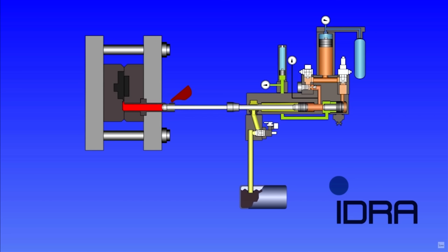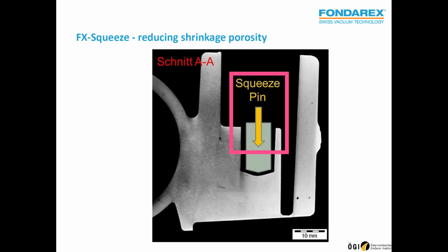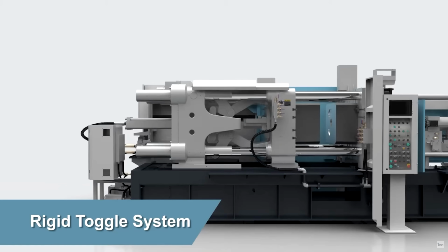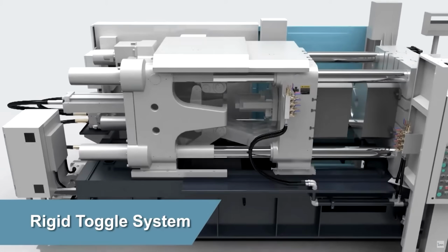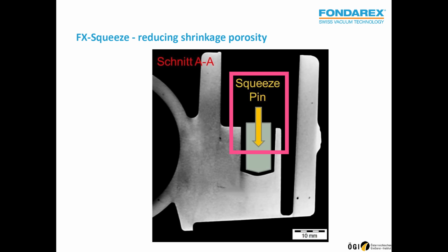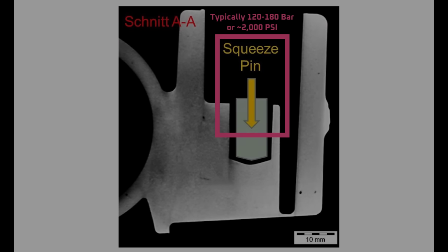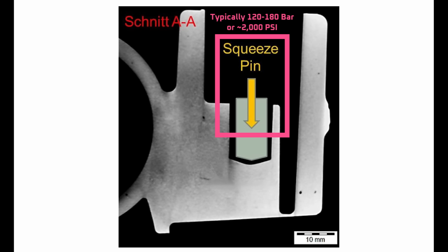That causes several issues. First, after the casting die is closed and the molten metal is injected, there's often little pressure left over to compress any pins within the die. That is, the available pressure drops as the die is squeezed together, which is just when it's needed to compress the squeeze pins. Second, with a typical squeeze pin system, the pressure supplied by the accumulator is usually about 120 to 180 bar, or about 1 ton of pressure per square inch, and they need more pressure to operate more effectively.